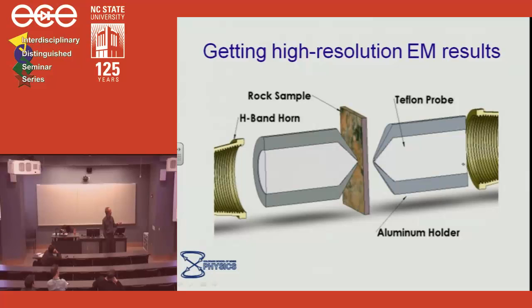So we use a dielectric cone here, and these angles are cut to optimize the critical refraction down here. And this is an aluminum shield to keep waves from diffracting out. And so you've got a very tiny hole here. The smaller, the higher the spatial resolution. And we've modeled this with finite element. And so if you're interested in all this kind of stuff, like the tip surface coupling, that's in the paper. I'd be happy to tell you about that.